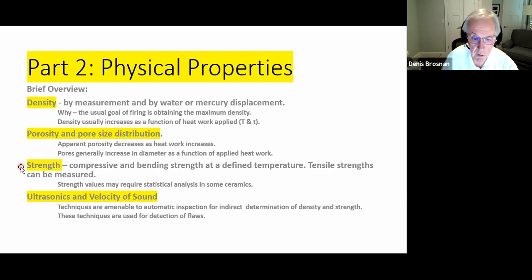We'll talk about strength. We'll talk about compressive and bending strength, and a way that tensile strength can be easily measured in the laboratory if that's something that is of interest to you. And of course, strength is a measurement of maturity, because typically ceramics gain strength during firing as they densify. Densification does something to increase the modulus of elasticity, the ratio of stress to strain of the ceramic, and that's directly related to some of the strength values that we have. Finally, I'll briefly talk about ultrasonics and the velocity of sound. These are very useful in production situations to gauge the maturity that you've achieved in the ceramic.